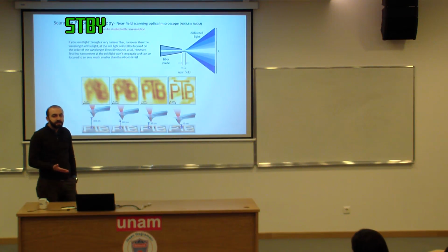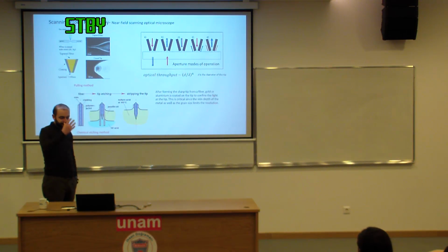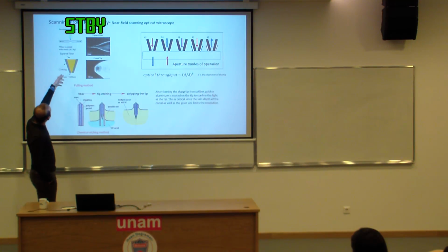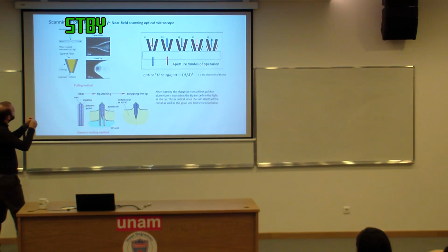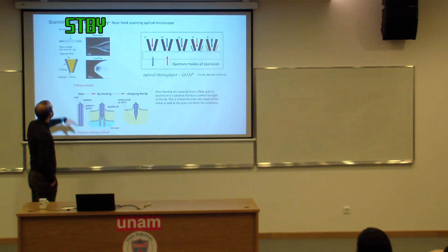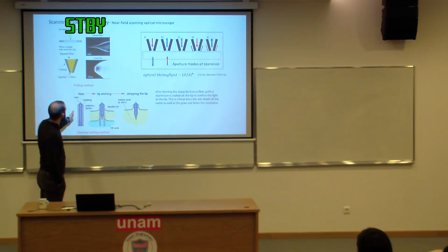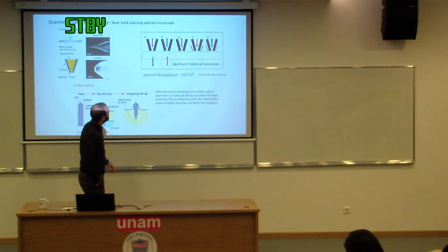Okay. So this is an extremely useful technique, because you can use light to probe things at sub-wavelength resolution. The way to do it is rather straightforward. There are several techniques. They have a fiber, they shine a carbon dioxide laser while pulling it, and the fiber gets tapered, and then they coat the sides with metals like aluminum and gold so that they can form this waveguide. And then there are also wet, chemical etching techniques. They coat it with certain materials, etch the cladding, the polymer jacket, and then with hydrofluoric acid, they etch the inner glass core. They form this tapered fiber.